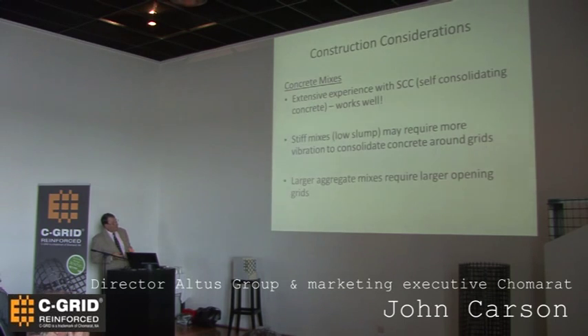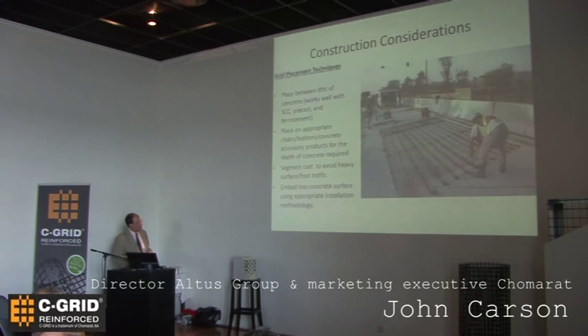So just a couple of comments relative to using the C-grid in concrete construction. Self-consolidating concrete has really been the most innovative mix design in the last several years. Carbon fiber grid works very well with SCC. If you want to use a non-SCC mix, you can. It may require a little more vibration to consolidate the concrete and get it around the grid. You need to make sure that the aperture of the grid is sufficient to pass aggregate through it. So that's one consideration for sectional designs.